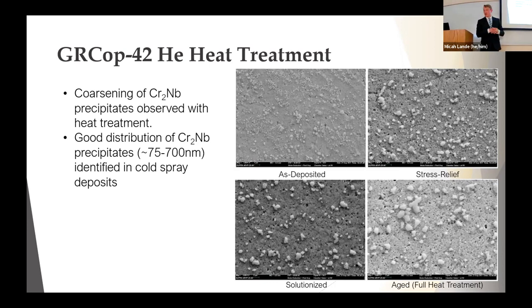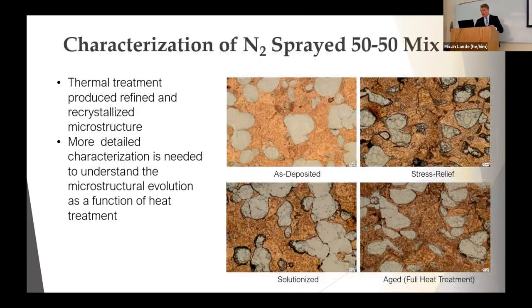That's also part of the reason why some of the mechanical testing as we go through the heat treatment process has lower values than we would expect, mainly because these particles are good to have. This secondary phase is good to have. However, when they start lumping together too much, we lose that dispersion strengthening, because it's not stopping our material from moving around, because they're all clumped together so much. And this is just looking at things with an optical microscope.